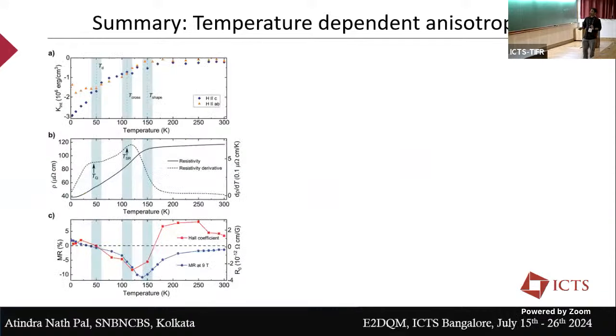So overall, now if we couple all the transport data and the ESR data, we can see that, of course, ESR data shows very rich anisotropy behavior, and it matches with the transport data as well. I told you that near the spin reorientation you have a transition, and there is a change of anisotropy, and at low temperature also you have a deviation. So that also you observe in the Hall data, magnetoresistance data, everything. So everything matches well, but we don't understand exactly why it is happening.